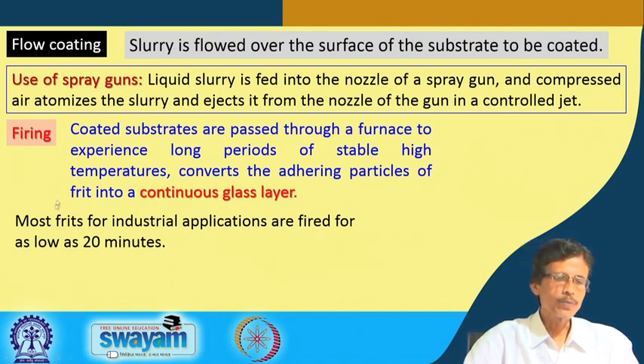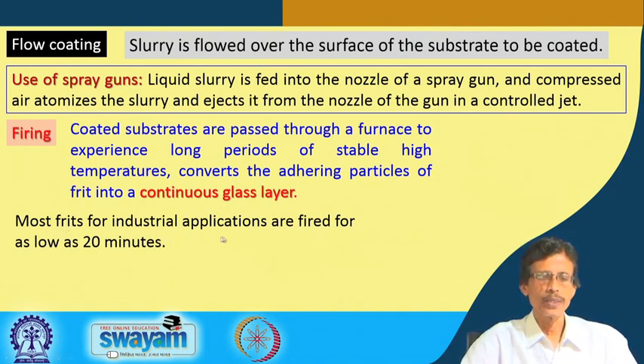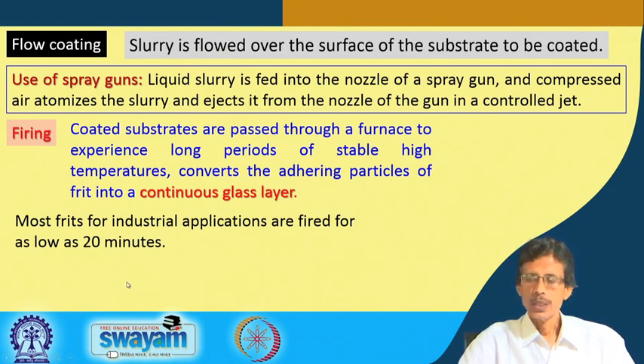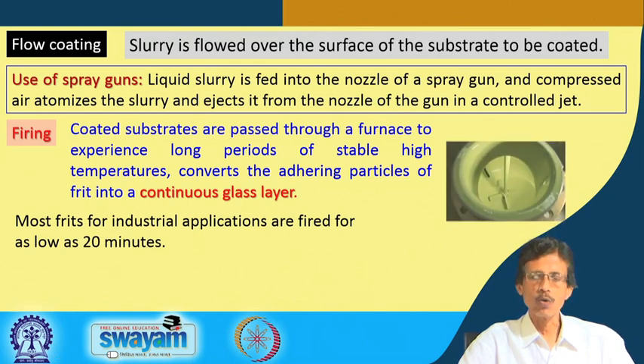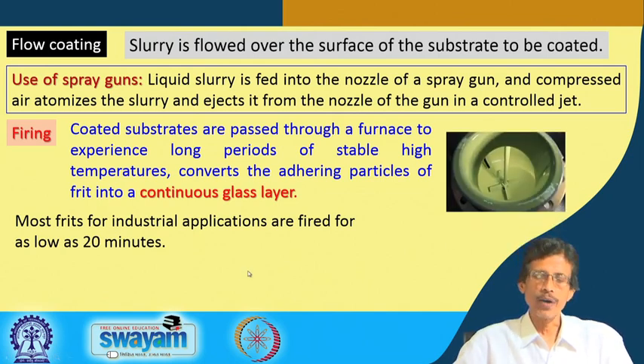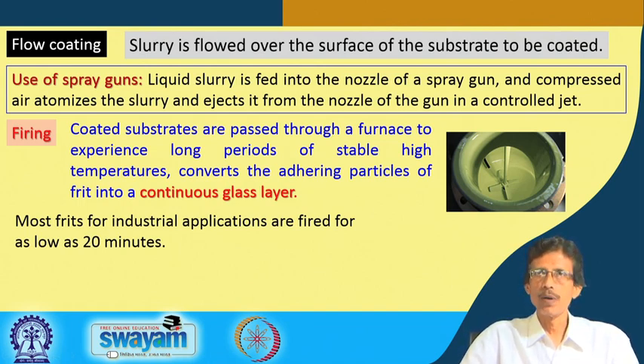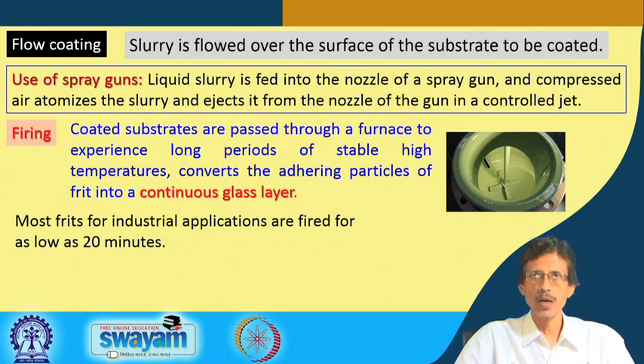For this particular use, most frits for industrial applications are fired for as little as 20 minutes. During this time of 20 minutes, we can go for the firing process, and that firing process gives you the corresponding coating. One such example that I am showing over here is that particular container. So, you can have a reactor, you see that it looks like that.